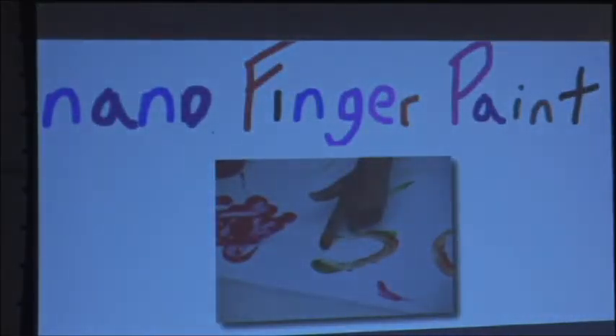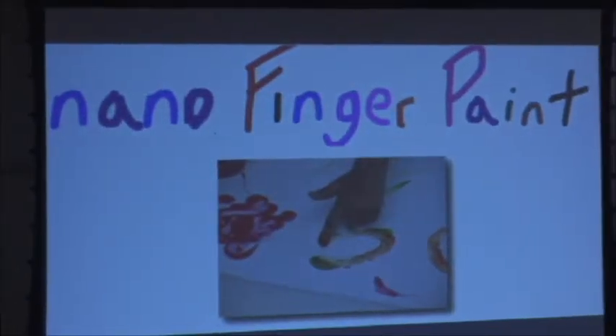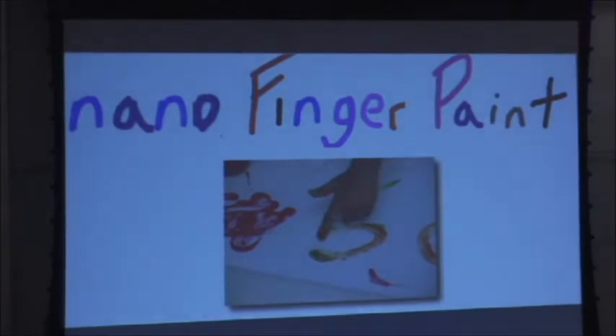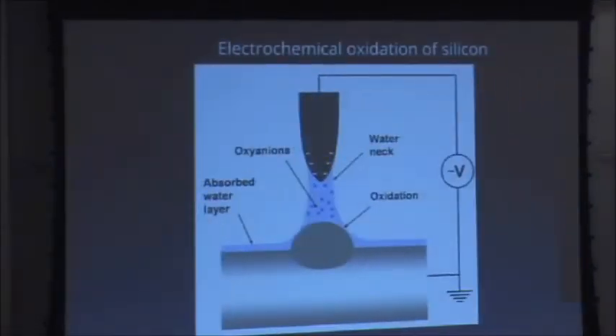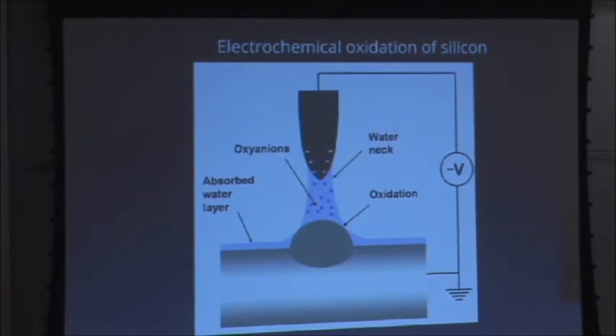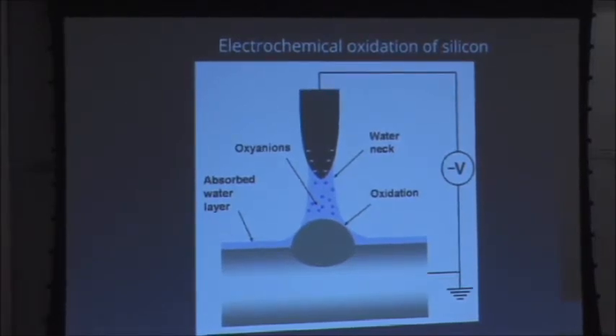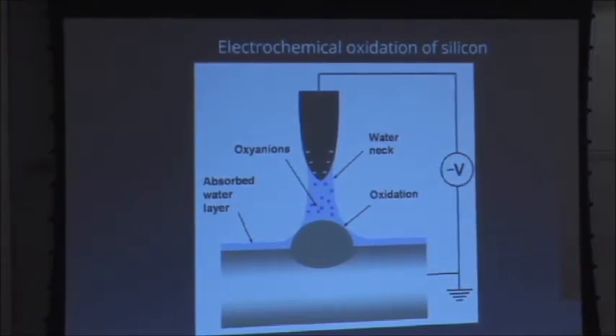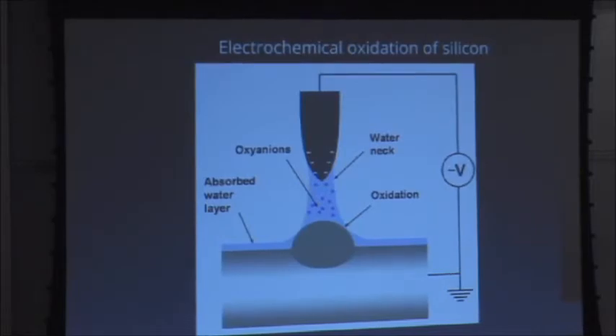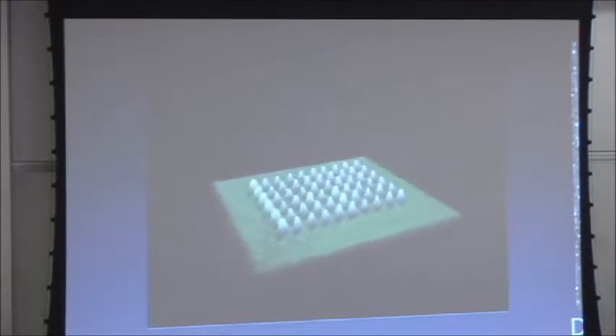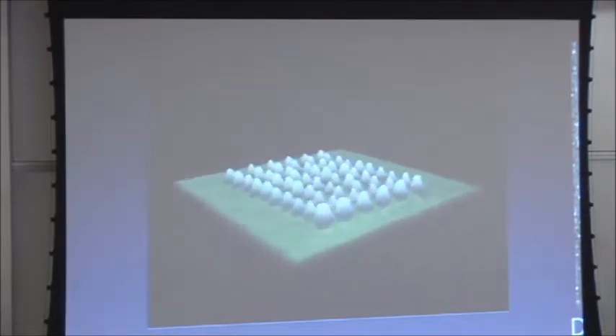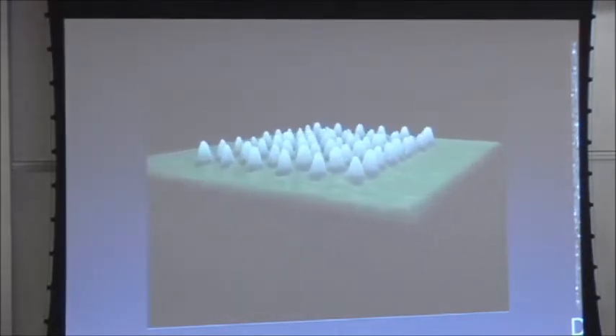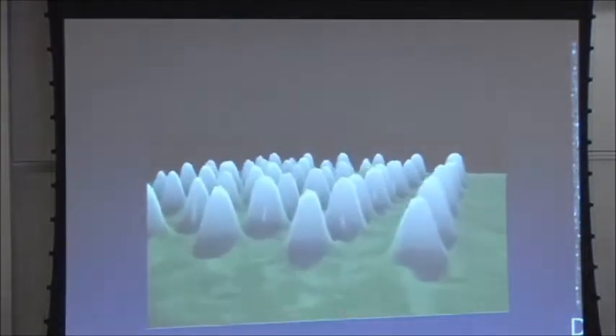And now here's really something that's completely useless. Wouldn't it be fun? So we've been oxidizing silicon by putting a minus 10 volts on the tip in a humid environment. The oxide takes up more volume, so you get a little structure on the surface. We did that first just with a spreadsheet, and just normal speed, wrote some dots about 20 nanometers across. Oxide's great because you can then reduce it and deposit other things in those locations.